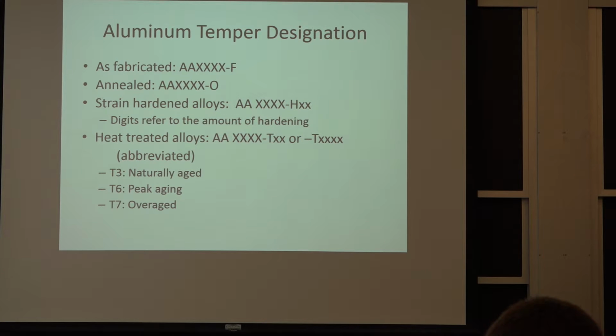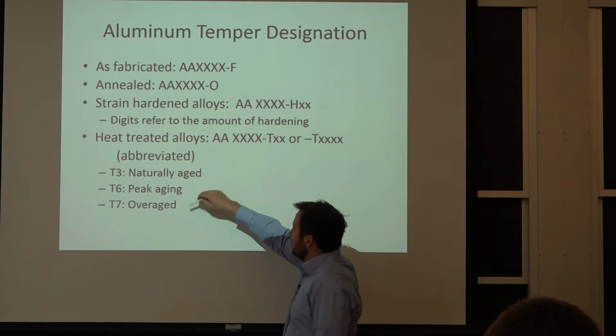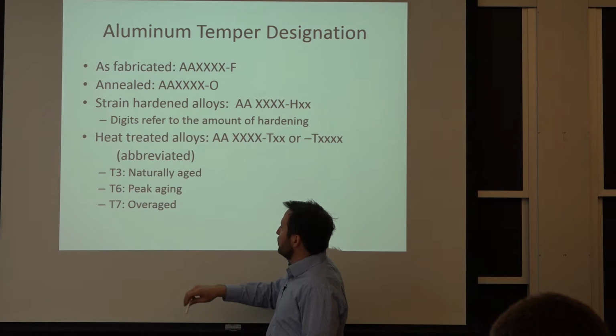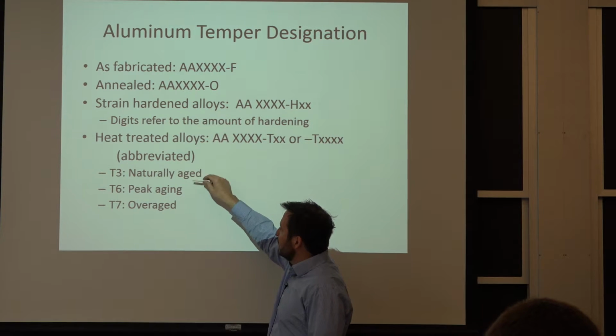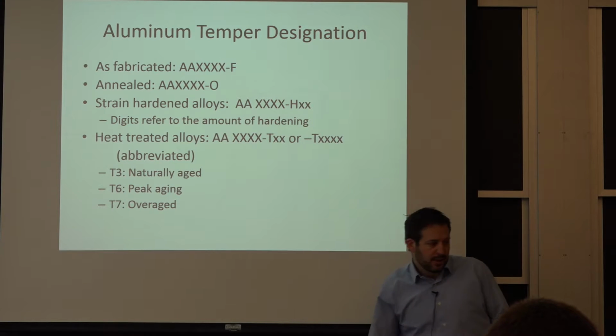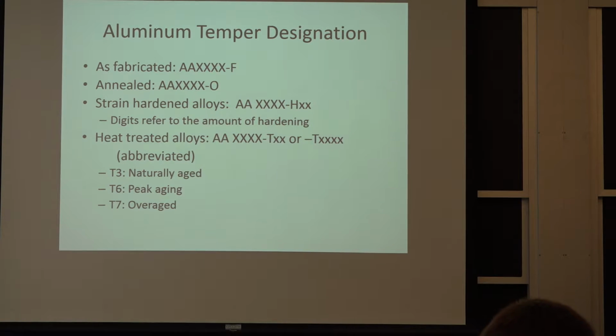We didn't go too much over the different heat treatment. T6 is the peak aging, but there are situations, if you have rivets, for example, to build an aircraft fuselage, it's very interesting how a lot of them work. You do the solution treatment, so you heat them up and quench them, and then you keep them in the freezer so they don't become harder.